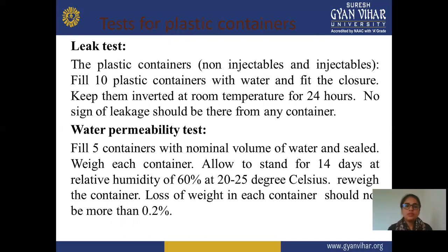This means after filling the bottles completely, you put them in inverted position at room temperature for 24 hours, and there should be no sign of leaking from any of the containers. After 24 hours you observe whether any leakage is seen or not.